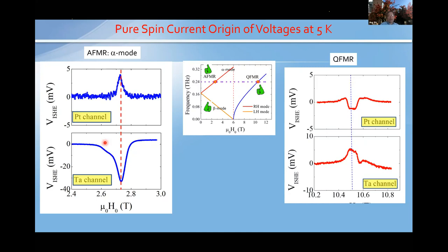One thing I also want to mention: when you look at the off resonance response, it's essentially flat, except in tantalum. There's a small background which, if you look over the whole field range, is linear in field, indicating that the ordinary Nernst contribution might be responsible for this background. Otherwise, off resonance, there's no other feature. When I say this, I didn't want to talk about the spin flop. If we forget about that feature, then off resonance we have an essentially zero response, indicating that the resonance features are essentially the spin pumping signal.